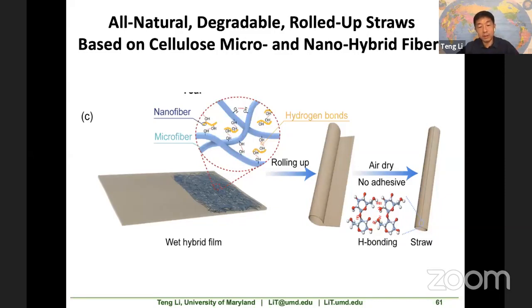First of all, it's dark. The reason it's dark is they need to coat the surface with a wax layer to make sure it is stable in the drink. And also they need to use glue to glue the paper together, which drives up the cost. So we use the microfiber of cellulose mixed with the nanofiber of cellulose to make a piece of film. And then we just roll it up. Because there are a lot of nanofibers of cellulose, when they are air dried, they naturally form hydrogen bonds to form the straw. You don't need any adhesive.